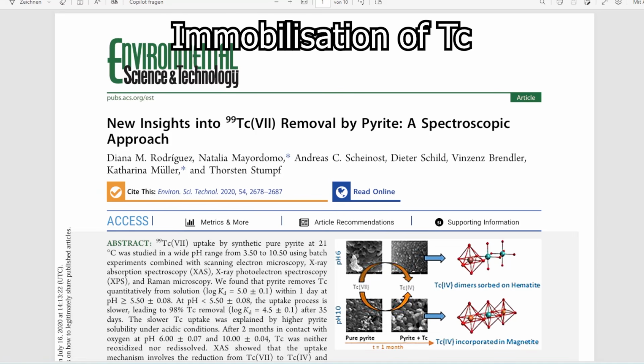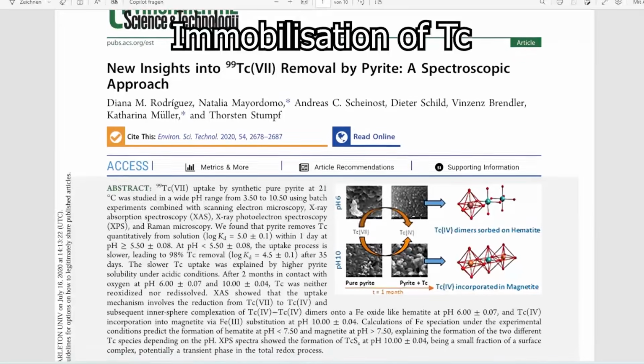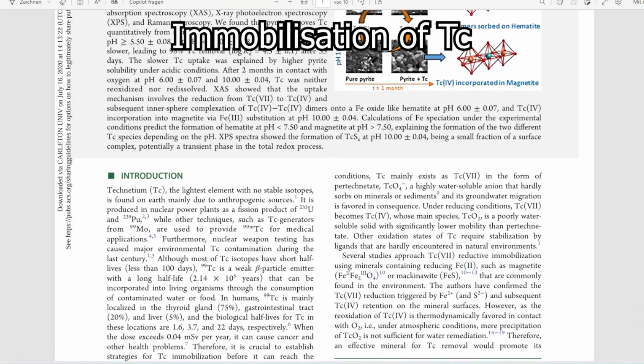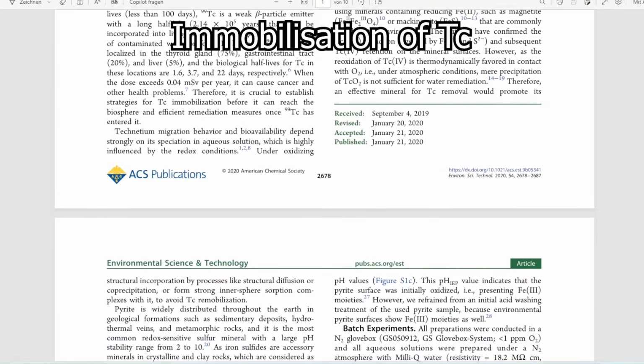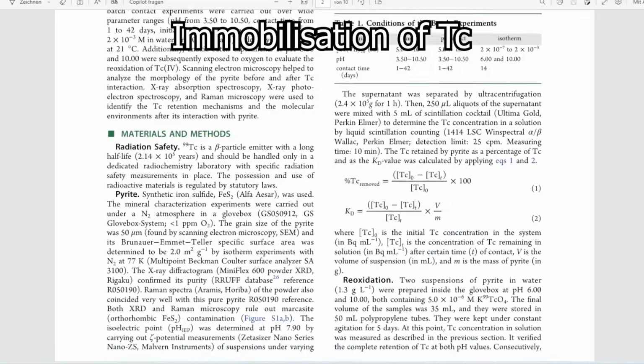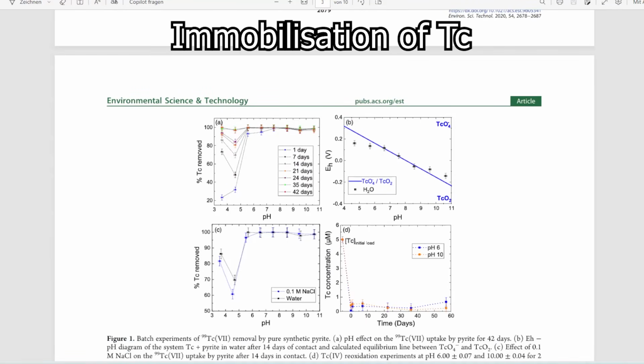It's a bit pointless to now show just a spectrum with hardly any technetium activity, but this is what we wanted to have. This experiment is based on a paper written at the HZDR. It was shown that at a measured pH value of about 5.5, 97 to 100% of the dissolved pertechnetate could be immobilized.